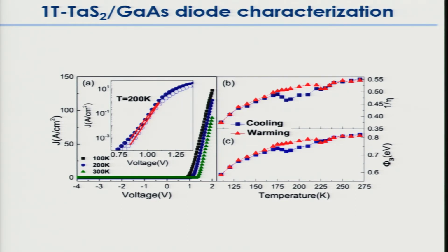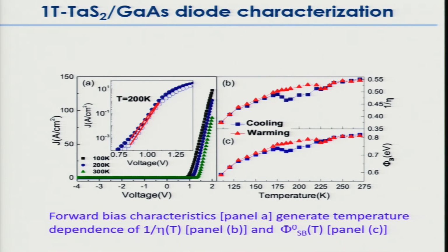We have a resistance which cuts us off up here, our idealities, and we plot 1 over the idealities for the cooling and warming. So on cooling, the ideality goes to a dip, and then it goes up. The ideality becomes larger as you cool down, but it has this dip. And the Schottky barrier height also has a region of hysteresis, which exactly overlaps the forward. So the forward bias almost fell off. This is the temperature dependence from the forward bias characteristics.